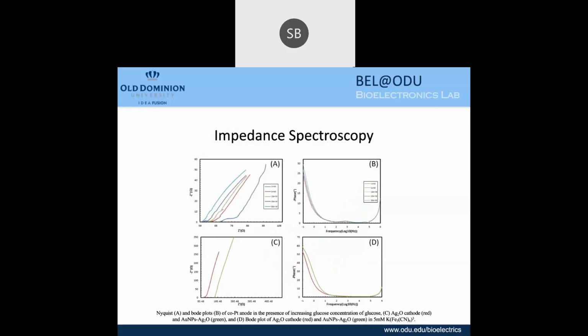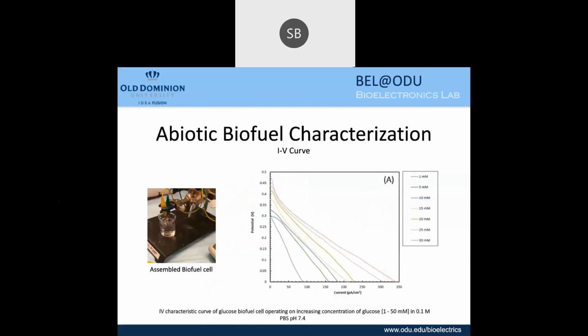This analysis is done using impedance spectroscopy, in which figures A and B show the performance of the anode with the increase in the concentration of glucose and the decrease in the resistance. And in figures C and D, the comparison between the silver oxide nanoparticles electrode and the combination of both shows the increase in the phase angle and the higher impedance, which were observed in 5 millimolar potassium ferricyanide solution.